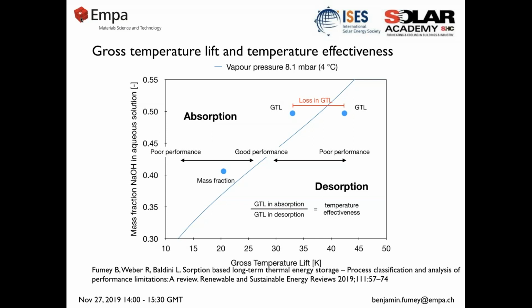And very important for heat storage here is we want to be able to perform close to this equilibrium line. And you also see that in desorption, the practical gross temperature lift is always going to be slightly greater than equilibrium. In the absorption, it's going to be less, and here we already can point to a loss in the gross temperature lift, or if we define it as the temperature effectiveness, it would be the gross temperature lift in absorption divided by gross temperature lift in desorption. This is also further alluded to in the below mentioned publication.